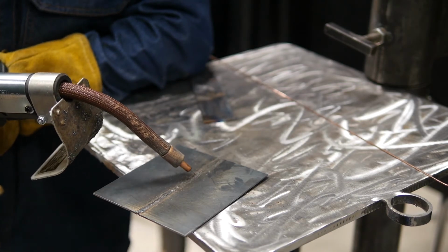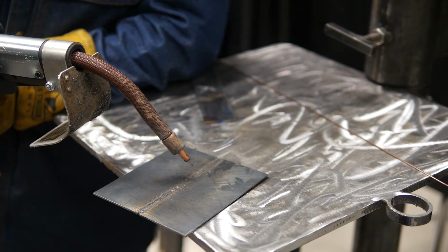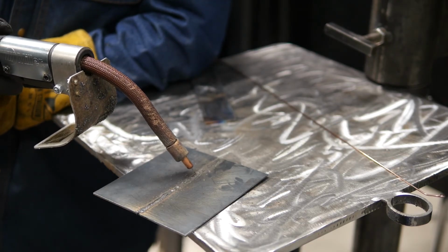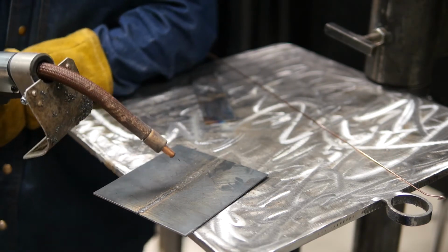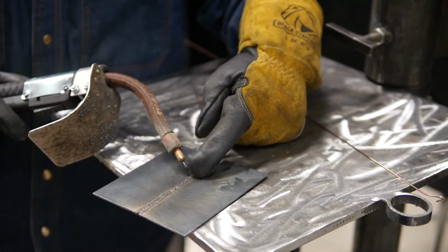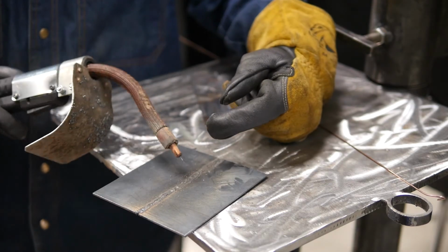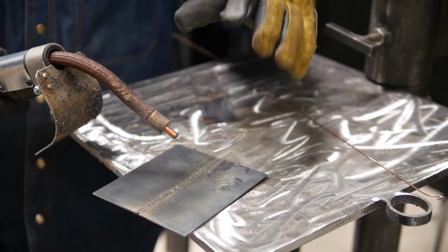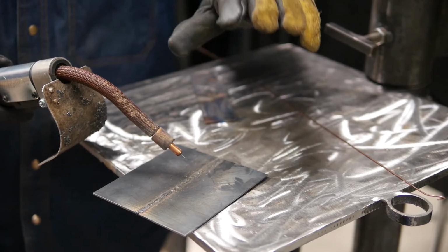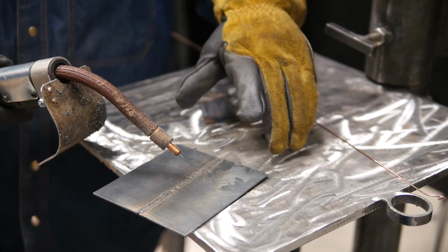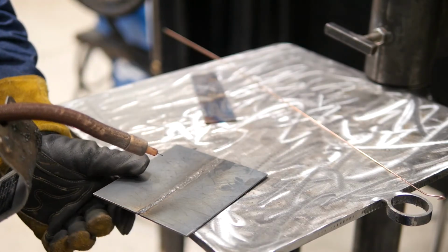The other thing we really have to pay attention to is contact tip to work distance. With this FluxCore wire, we only want to be sticking that wire out around 1/4 inch. I've got to make sure that stays nice and tight, especially when I'm running this wire in our lower amperage and our low procedures. Let's destructively test this coupon.